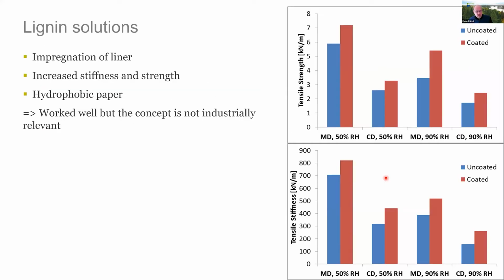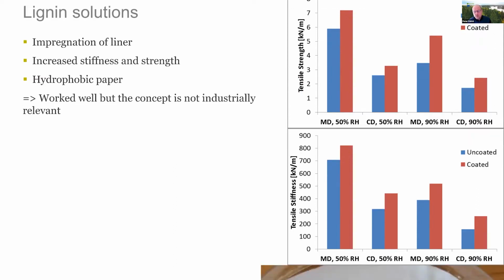Anyway, if we solve it, we can actually make a hydrophobic paper. I don't know if we actually have a phase where I use a hydrophobic paper, and this is something that was done 15 years ago, and the papers are still quite hydrophobic. But the interesting part was that when we put a coating onto it, we increased the strength and the stiffness quite considerably, even at high relative humidity. So for that particular way, it's kind of interesting. The hard part is to put it in water.